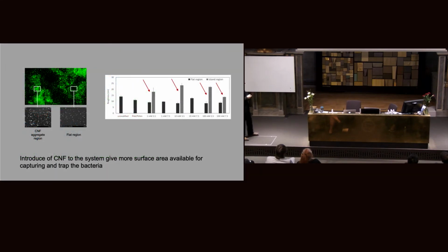And if we measure the roughness of the island regions or aggregates versus the flat parts, we found they have a much higher roughness. So a plausible explanation about why the CNF samples are better than the PPA ones, we think is because we introduce CNF to the system and give it more surface area and more roughness to allow the surface to capture and trap the bacteria.